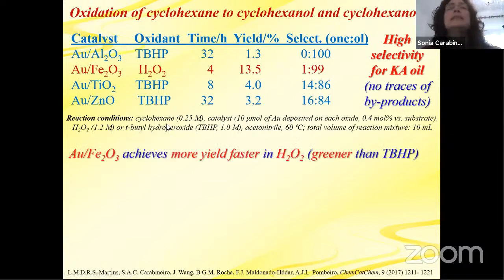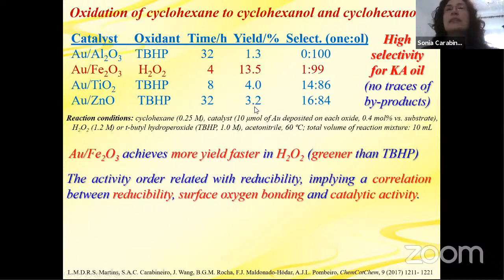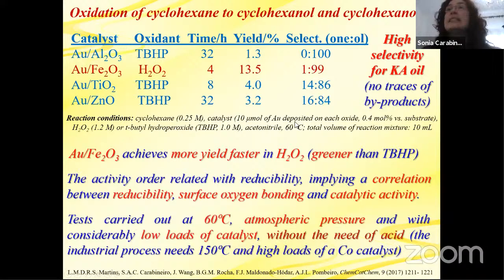selectivity. So this gold on iron oxide achieves more yield and faster in this oxidant, which is the greenest of all. And the activity order you see here is related with reducibility of the support, because this is a very reducible support and others are not. And this implies also a correlation between the reducibility of the support and the surface oxygen bonding to the catalytic activity. And these tests were carried out at 60 degrees Celsius, atmospheric pressure, and with low loads of catalysts, and without the need of acid, because the industrial process needs very high temperature, 150, and high loads of a cobalt catalyst. So as you see, we obtain here 13% yield, which is above the industrial process.